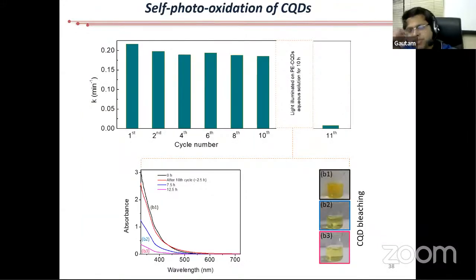So we found something very interesting in the laboratory. We were doing this dye degradation reaction. You saw those color dyes. By mistake, what happened? We were doing these cycles, and from the first, second, third, fourth, up to the 10th, the efficiency is more or less similar. But between the 10th and 11th, we kept the light on the carbon dots a little longer, after the dye was gone. Then in the 11th cycle, the efficiency became less. Then we started looking into it.